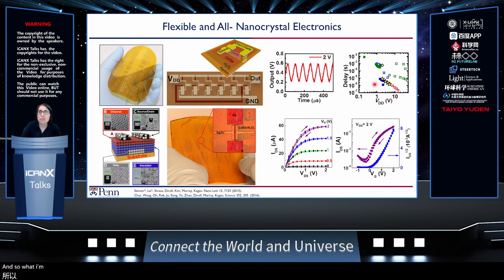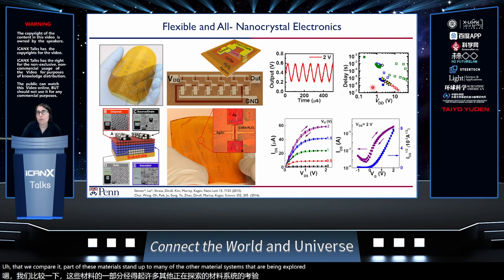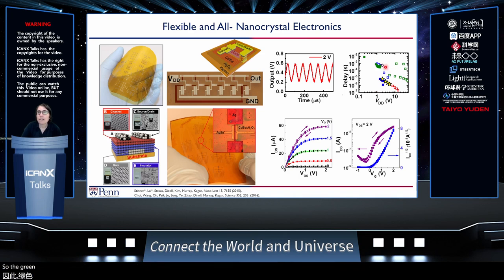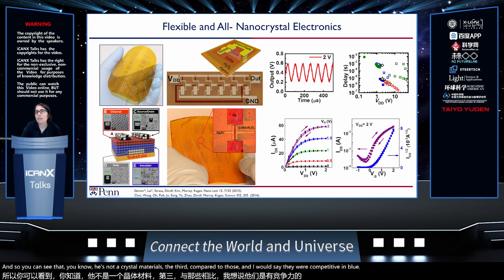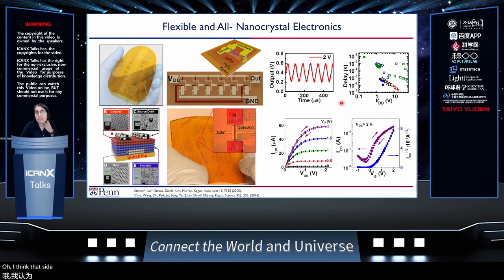What I'm showing here is that, at the time that we did this work, we compared how these materials stand up to many of the other material systems being explored in the community. The green are organic semiconductors used in transistors. If it's filled in, it's on a rigid substrate, and if the symbols are open, it's on a flexible substrate. You can see that these nanocrystal materials look good compared to those, and I would say they were competitive. In blue and red are examples of carbon nanotube arrays and sol-gel zinc oxide. They're an interesting competitive material system, we'd argue, for applications in flexible electronics.